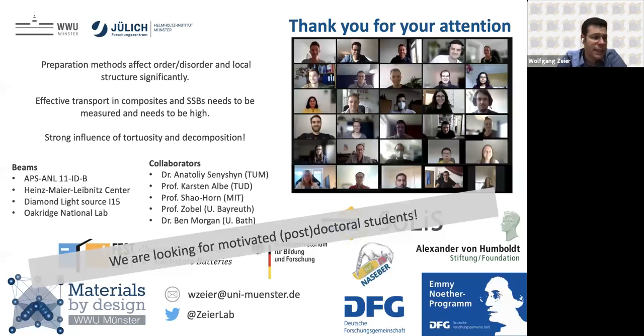We see that in certain materials, there's residual features in the PDF that can hint at an amorphous background, if you do a differential PDF, where, for instance, we just see these PS4 signals. A few years ago, we interpreted that as a glass phase. There's newer work that suggests that is actually additional PS4 disorder that is just not mapped out. There are certain materials that seem to have additional glass phases, and that seems to depend on the composition. So the honest answer is it's magic.